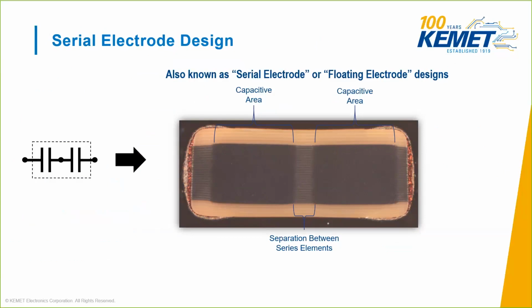Now, because there are effectively 2 capacitors in series in this example, if one were to short due to a crack, the other element would block the DC current and theoretically fail open. Note that the flex crack cannot cross multiple electrode patterns originating from both ends of the capacitor. It can only cross the electrode pattern where it originates from, and there will be floating across the active series. Therefore, these capacitors are also referred to as fail-open technology, which is commonly used for applications with potential for high DC currents, such as battery lines.